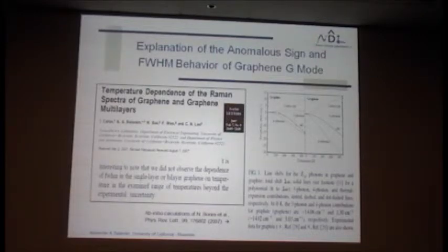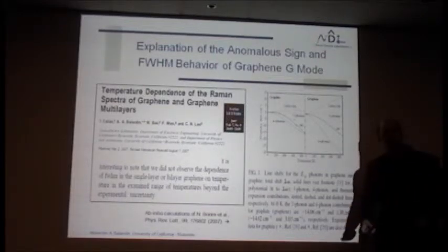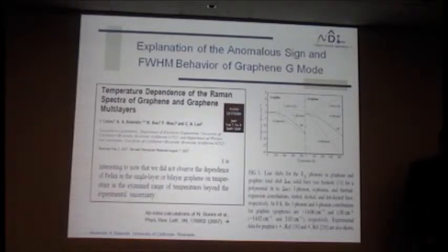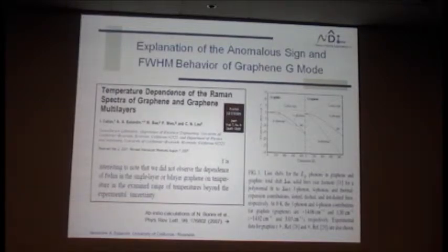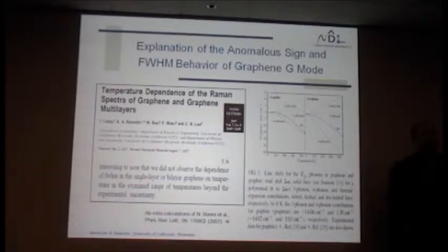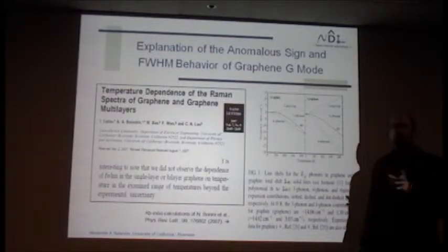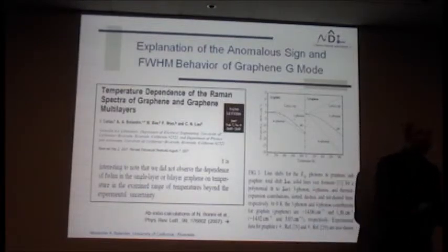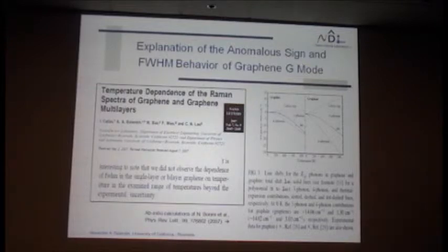So that gave us confidence that what we are measuring is indeed resulting from the heating we produced. And so it is a good metric to measure the temperature. Now when we did these measurements, I want to clarify one important point: we intentionally used very low excitation power of the laser so that we don't produce local heating. Instead we change the temperature of the setup externally. That kind of gives us a calibration curve.